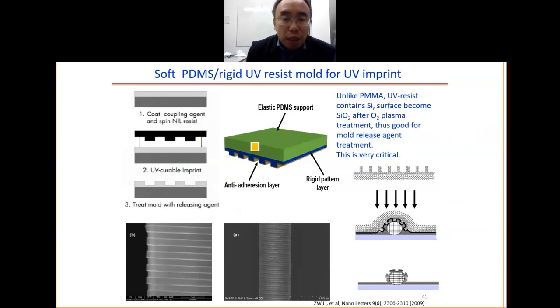This one is good. This one you can have very low surface energy. You can have this anti-adhesion layer give you low surface energy. This one, the backbone is the PDMS. This is a soft plastic. Because it is plastic, you can do the imprint onto a curved surface. You can see here, you do the imprint on the optical fiber because the PDMS is flexible. It's very, very flexible, soft.